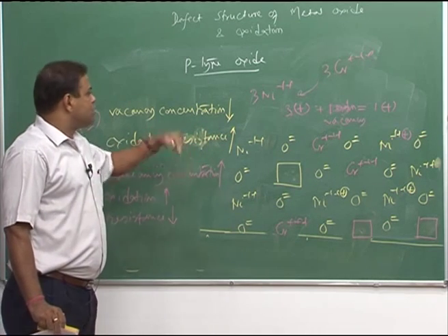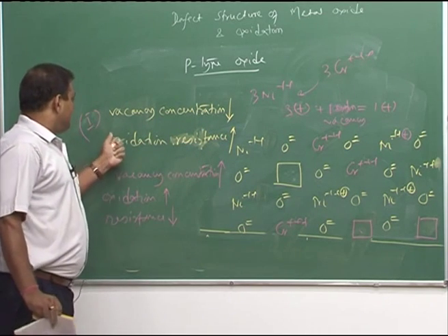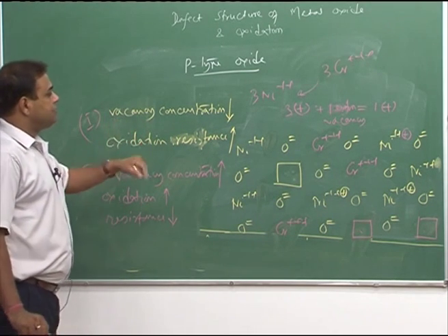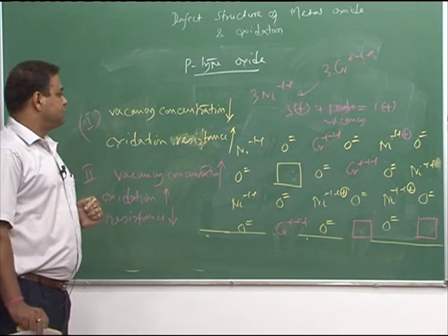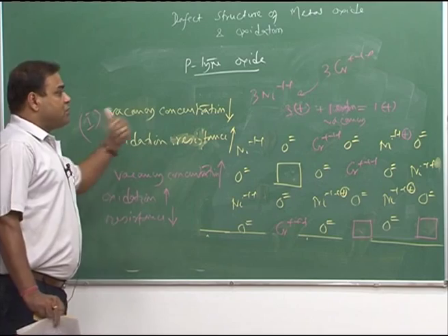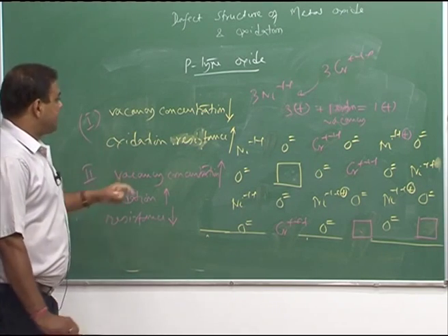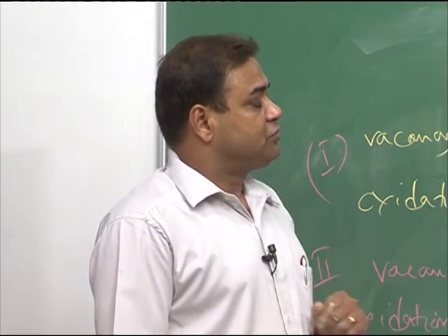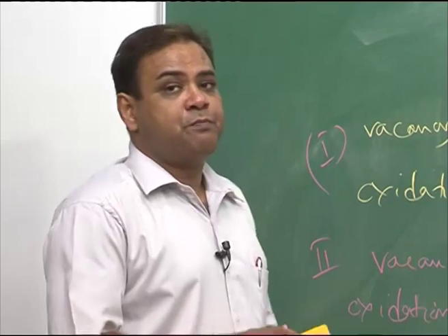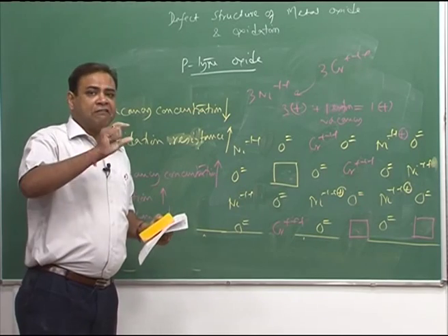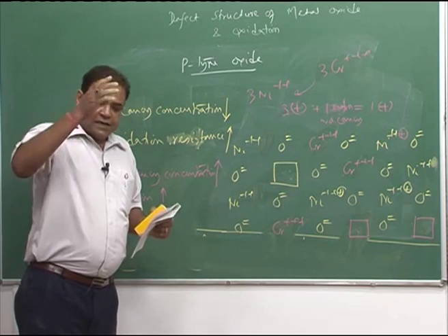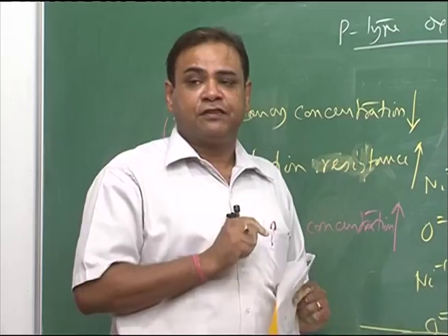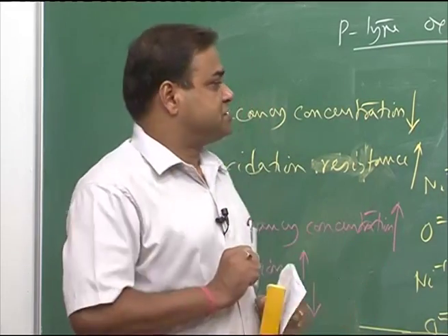Now, in case of doping, in order to have this benefit of increased oxidation resistance, we need to dope it maximum up to 5%, but if it is beyond 5%, the situation would be different. For example, in case of chromium addition in iron, if chromium content is beyond 18%, instead of an FeO layer there could be formation of a Cr2O3 layer, and if the Cr2O3 layer forms on the surface, then it could give a very good oxidation resistance.